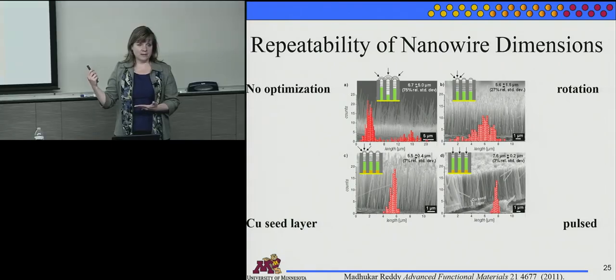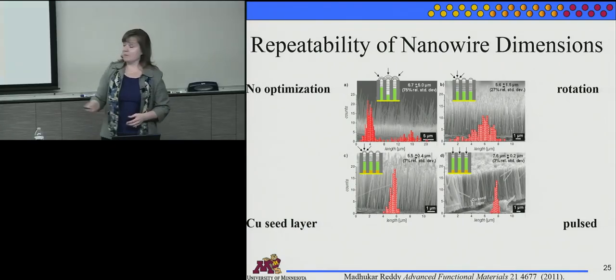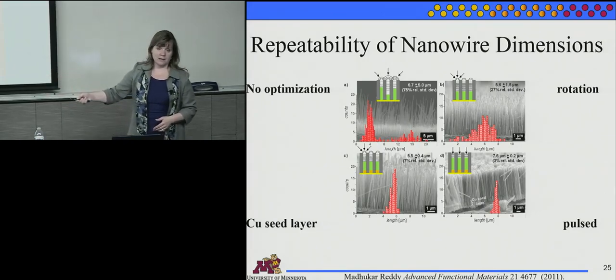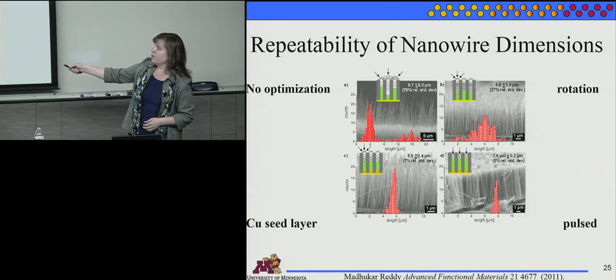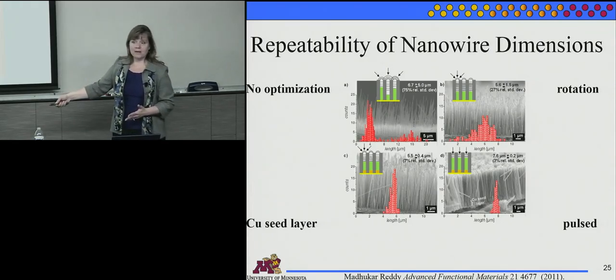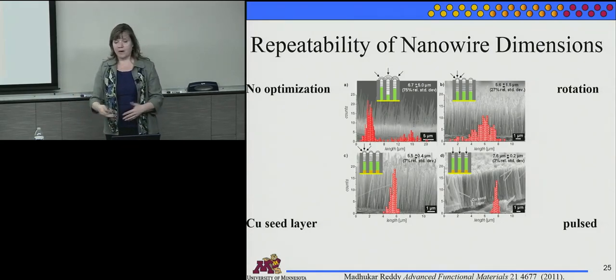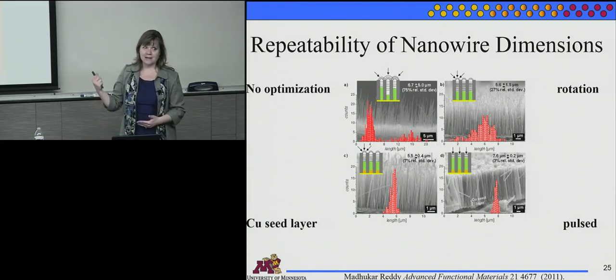except for a couple alloys, right? This one's not very uniform. This is actually iron gallium. And here you can see there's a whole lot of short ones and these weird long ones. And this is a histogram of it, a whole lot of short ones and some weird long ones. Not at all what we want. If we're going to try and make a certain property and we want all the sample to have the same property, that's not going to do.